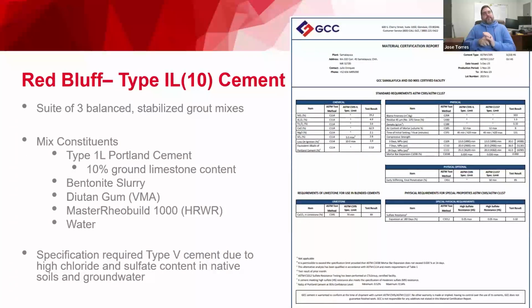And then for Red Bluff, where we are currently, we're using type 1L cement with a 10% ground limestone content, and we're using about 3 mixes here. The funny thing is the specification actually required the use of type 5 cement, and we asked for a variance. It asked for type 5 because of high chloride and sulfate content in the soils and groundwater, so the mix had to have some high sulfate resistance. We found and sourced this type 1L10 cement, and it passed testing for high sulfate resistance, so we asked for a variance and we're using 1L here on the job.